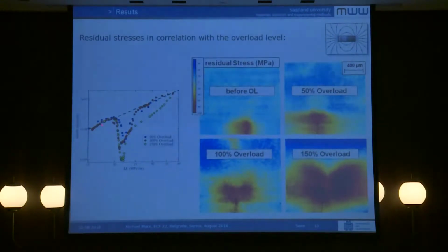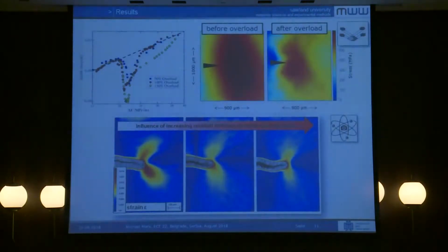This is the a over N diagram after the overloads, 50%, 100%, 150%, and these are now the residual stresses measured by the Barkhausen noise before the overload. Here just the compressive stresses from the cyclic plastic zone, and here from the overload zone, and as expected you have an increasing zone with residual stresses with increasing overload. Here now you have the loaded crack tip before the overload, and this is the loaded crack tip after the overload, so it may be somewhere around here, and you see now that your tensile stresses are reduced.